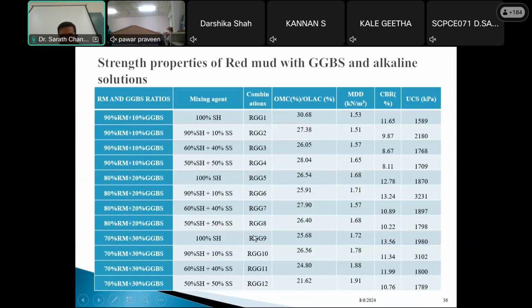And next are RGG7 and RGG8. RGG7 is 60% sodium hydroxide, 40% sodium silicate. Next, RGG8 is 50% sodium hydroxide and 50% sodium silicate. Why did we study this? Instead of using just one material, if you apply sodium hydroxide and sodium silicate in different concentrations, how does it work? That's what we studied here. Among all of these, 90% sodium hydroxide and 10% sodium silicate, that is RGG6, has given the best result for both CBR and UCS.